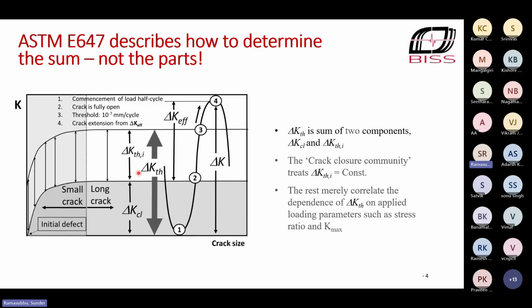There is the other part, which is the intrinsic threshold, which is a subject of controversy, because the fracture mechanics community has two parts. The crack closure community, which is very loyal to the concept of crack closure, believes that intrinsic ΔK threshold is actually a material constant, and that it can even be theoretically determined from dislocation dynamics, depending on modulus and parameters like that. The rest of the community doesn't believe in crack closure anyway, or treats it as an unreliable and inconsistent phenomenon. And it just correlates ΔK threshold, the sum of the two.